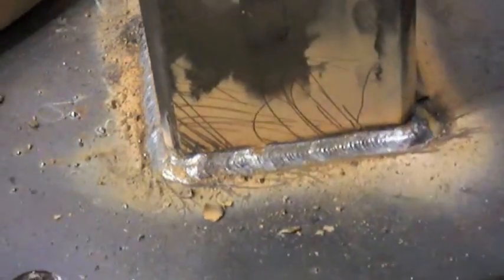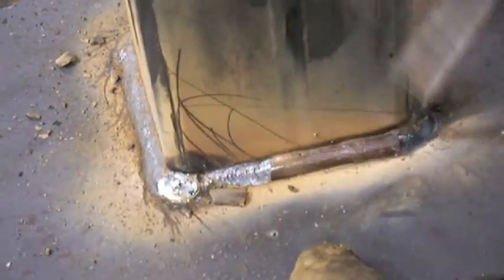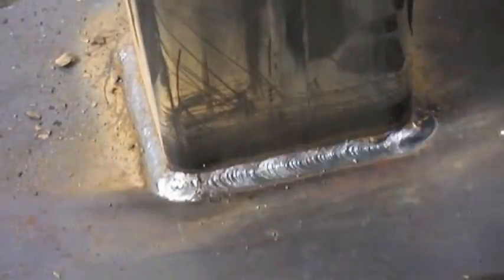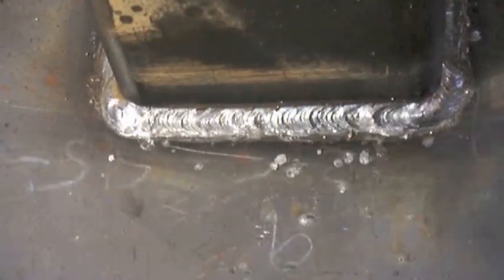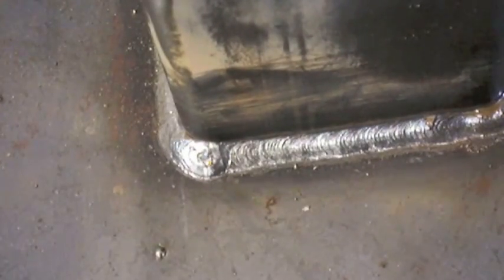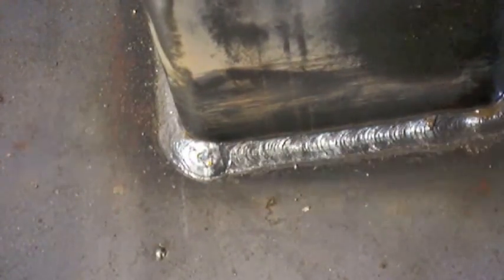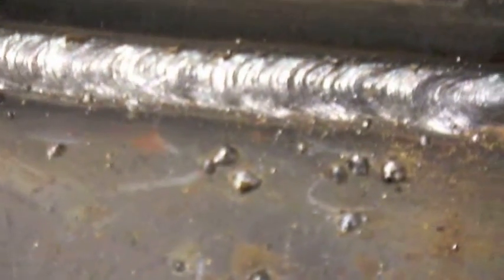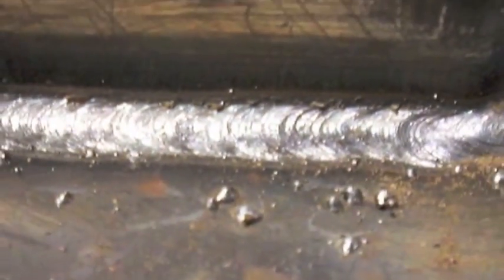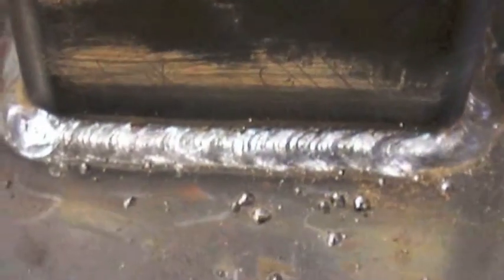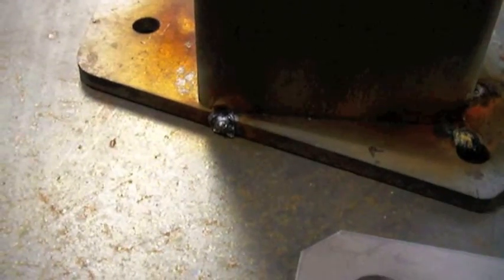We'll get this cleaned up. In a minute here, I'll show you that first bead. It was welded at about 10 or 20 amps hotter than it should have been. See all those big BBs there? I chipped them off already. BBs like that - that's just the metal kind of exploding down in there and popping out. It leaves a little low place on a ripple when it does that. No big deal. It's not really a flaw. It just takes time to take a cold chisel and chisel them off.